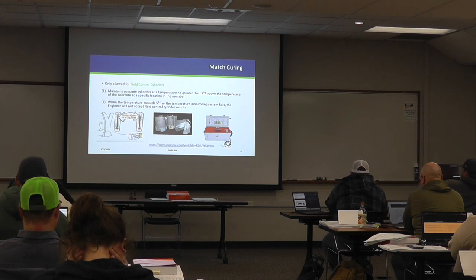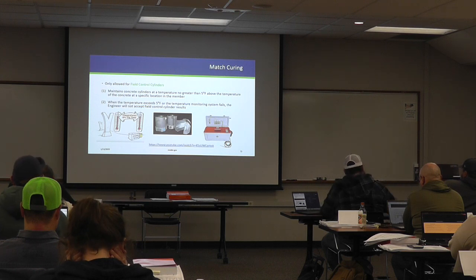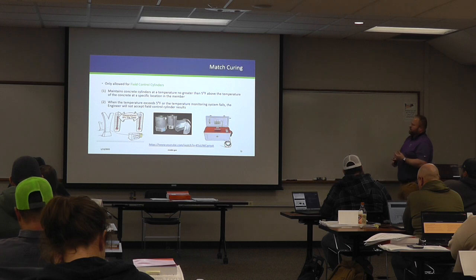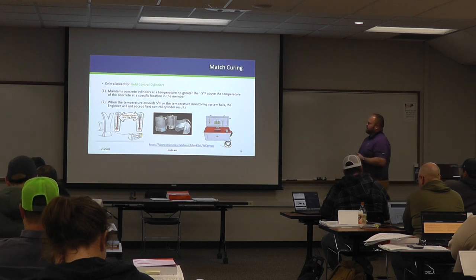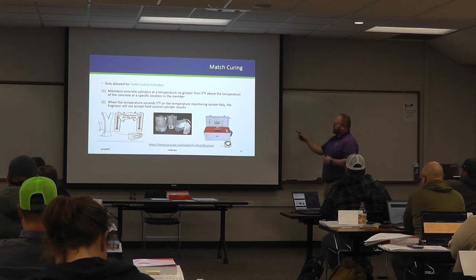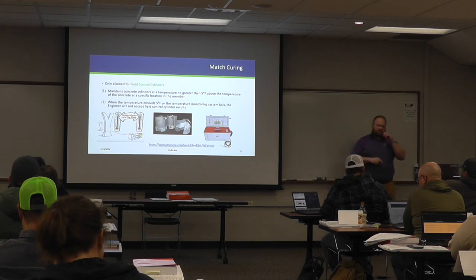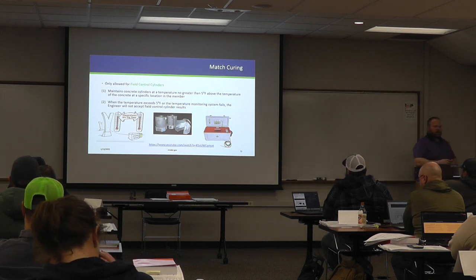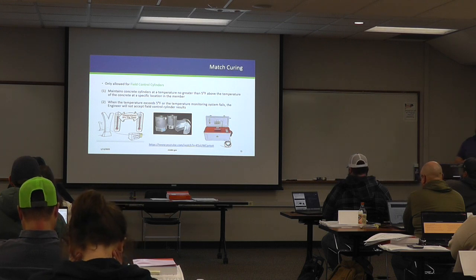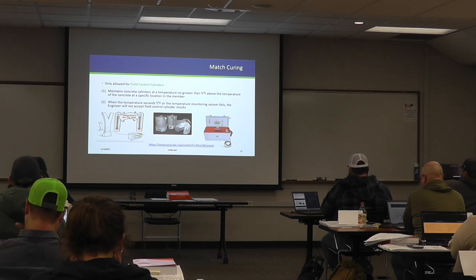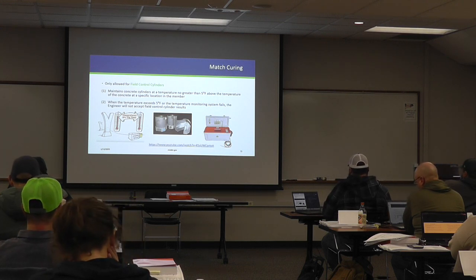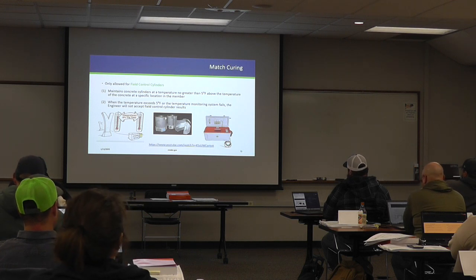So if we're using this, we want to maintain those cylinders at a temperature no greater than 5 degrees above the temperature of the concrete out in the field. And then if the temperature exceeds that 5 degrees or the temperature monitoring system fails, that's a part of these match cure systems, then we're not going to accept those field control cylinder results because they're not valid anymore, right? Especially if it gets above 5 degrees, because if they get more heat, they're going to have higher strength than what's out in the field.